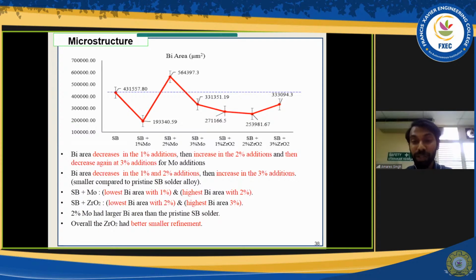Looking at the zirconia first, all 3% of additions gave us a measurement of the Bi area which is lower than the SnBi. Whereas for the molybdenum addition, only the 2% had a higher Bi area measurement compared to the SnBi. There is a reason behind this that is related to the shear strength or intermetallic compound. Upon study of the microstructure, I have seen a small amount of molybdenum at the solder side. Most of the molybdenum for the 2% has attracted itself to the interfacial layer.